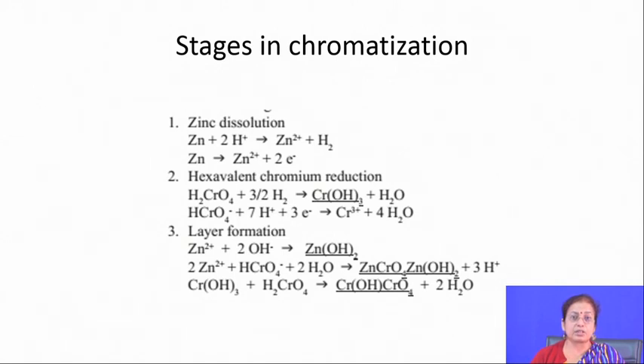If you see the stages of chemical reaction, with hexavalent chromium, first there is dissolution of the zinc if you do chromate coating on zinc surface, and then hexavalent chromium reduction is there, and then there is layer formation. But when you use trivalent chromium, then that second stage is no more there, and you directly create chromate on the surface of the zinc.